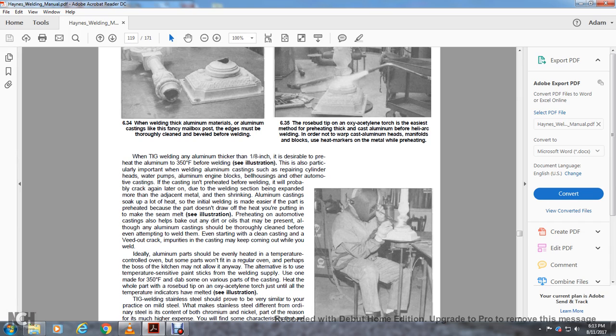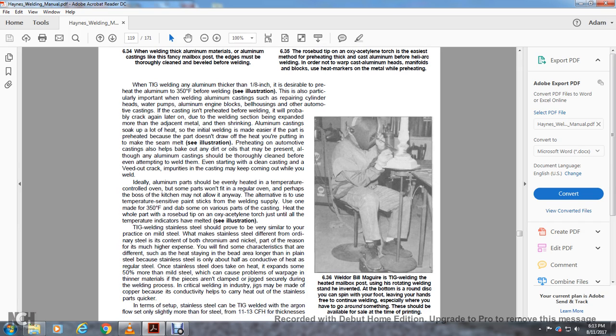Even starting with a clean casting, the bead may crack, as impurities in the casting may keep coming out during the weld. Ideally, the aluminum parts should be evenly heated in a temperature-controlled oven, but some parts won't fit in a regular oven. Perhaps the boss of the kitchen may not allow it anyway. The alternative is to use temperature-sensitive paint sticks from a welding supply. Use one made for 350 degrees, dabbing it on various parts of the casting. Heat the whole part with the rosebud tip on the oxyacetylene torch until all the temperature indicators have melted. See illustration.